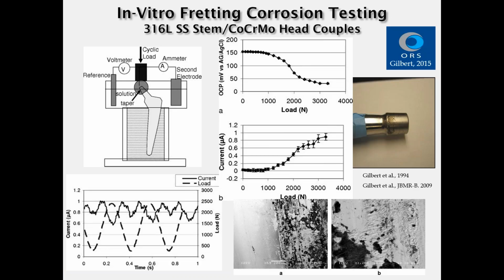Additionally, we've been able to model and mimic much of the mechanically assisted corrosion process in the laboratory in relatively simple tests like this one that we published in 2009, but has its precursors going back to 1994, where we can apply cyclic loads to the head of a femoral component and monitor both the voltage of that component as well as current that would be generated from the fretting corrosion passing through to a second electrode. We've noted that these currents will rise with the increase of the cyclic loading, and that the overall voltage of the system can become more negative as a result of the abrasive and repassivating processes.